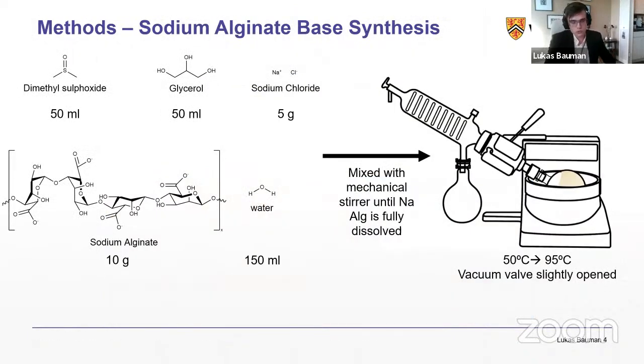So the first difficulty with this is sodium alginate is really only soluble in water, and it's quite viscous in water. So what we did first is we dissolved the sodium alginate in a water solution with dimethyl sulfoxide, glycerol, and sodium chloride. And then we evaporated the water in a rotavap. What this allowed us to do is disperse the sodium alginate in the glycerol dimethyl sulfoxide mixture after removing the water, because if you try to just dissolve it in glycerol, you can't. So you end up with a very smooth, almost paste.